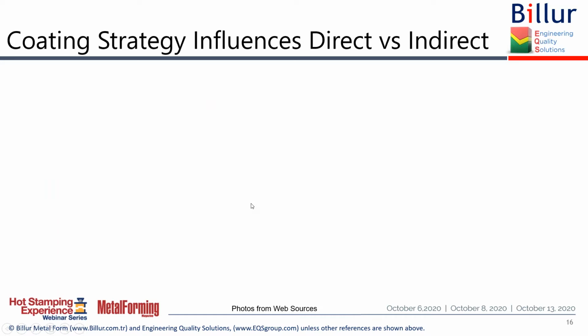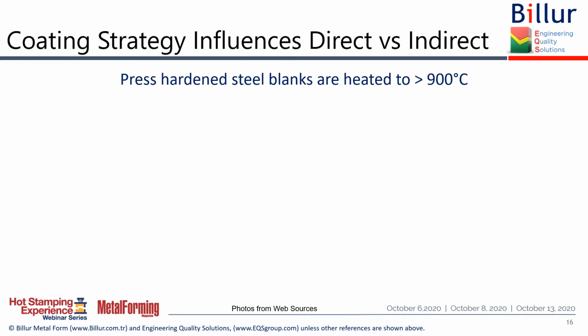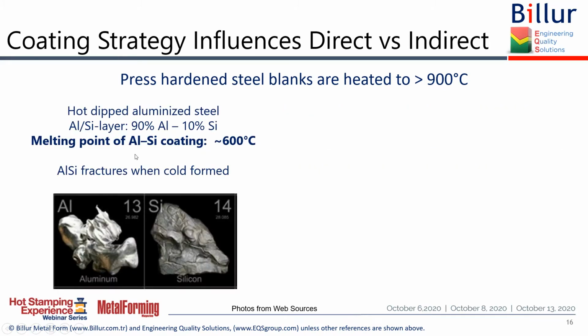The main difference between the direct and indirect process has been the coatings. So we heat these blanks over 900 Celsius, and when you have the aluminum silicium coated blank, the problem is you would have the melting of the aluminum silicium coating, approximately around 600 degrees. And this would cause a lot of problems if you have a roller hearth furnace. Your rollers may be contaminated due to this melting, and you could have a lot of maintenance issues.